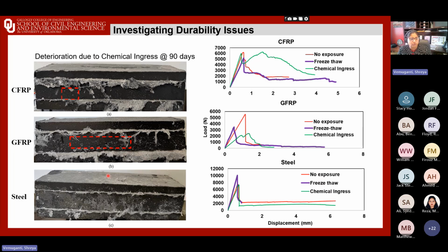You can see how the reinforcement experienced that sort of damage, mostly because it's external and there is an overhang. But to understand more of the flexural performance of these specimens, if you look at the right side graphs, these specimens showed some degradation in mechanical strength, especially GFRP. For the glass fiber reinforced polymer, we could see up to 56.5% reduction in the chemical ingress alone. And this, of course, relates back to how chemical ingress can accelerate corrosion and deterioration at the composite concrete interface.